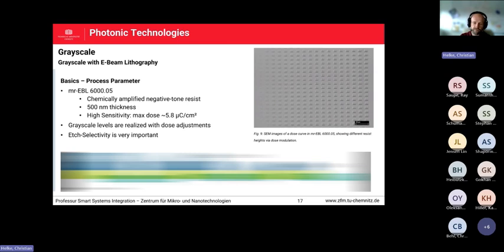And then what is very important, you have to etch the material below. So for example, the 500 nanometer silicon dioxide. And for pattern transfer of a 3D or 2.5D structure, it's very important that you etch the material below the photoresist and, at the same time, etch the photoresist away, so that you really can deal with the complete pattern transfer into the material, for example here, the 500 nanometer silicon dioxide, whereas the photoresist is already used up, so that you don't have some residuals on top, and then the whole layout is transferred into the material below. So it's always a trade-off between etch selectivity of the material, etch selectivity of the photoresist itself, and the pattern transfer of the structure, in this case the 3D structure, into the material below.